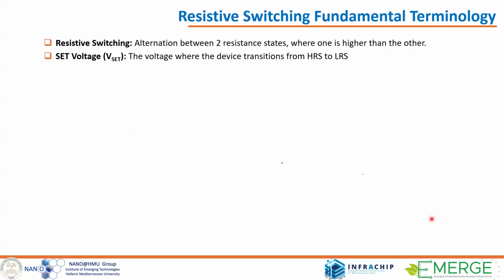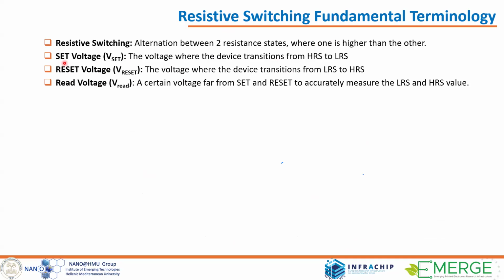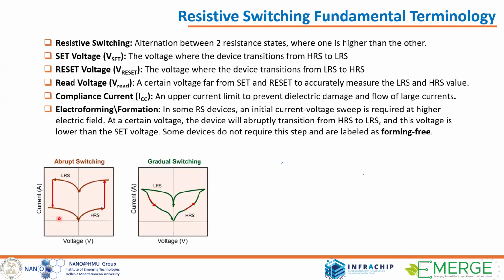A few words about the main KPIs. The device in principle has two different resistance states. We call them the high resistance state and the low resistance state. Of course, we can have intermediate states in between, depending on the device. We have a standard set voltage. Maybe I can go down to see the graph. So here in the typical IV characteristic, the device starts at high resistance. When we exceed the threshold, the device jumps to a low resistance state. This is the current, this is the voltage. And then the device stays at low resistance until you exceed the threshold of the other polarity, in order to reset the sample to high resistance. So it's a typical abrupt switching of a memristive device.